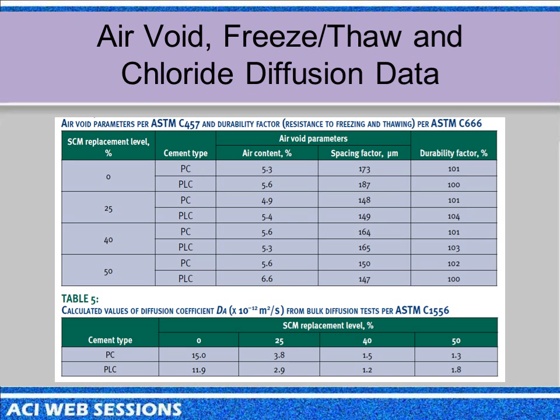We did air void spacing factors on these things, and they're all good. They're all less than 200 microns or 0.008 inches. And they all had a 100% durability factor in the C666 freeze thaw test. Chloride diffusion results are pretty much the same. The big difference, of course, is big reductions with the pozzolan replacement levels of the cement.